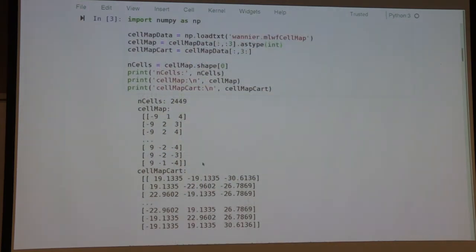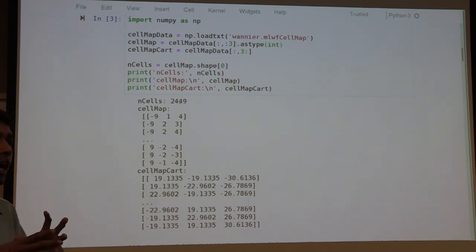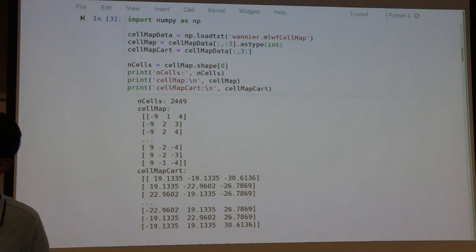If you look at the number of cells in this Wannier expansion, it's a couple of thousand. So while these are termed tight binding Hamiltonians, these are actually accounting for the interaction between the electrons over quite a decent range compared to the next lattice site.